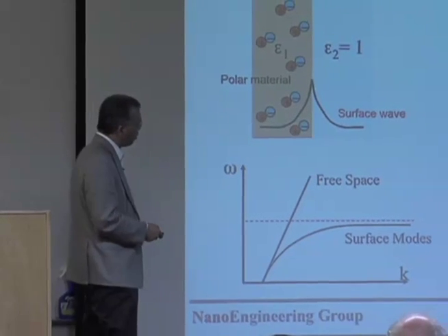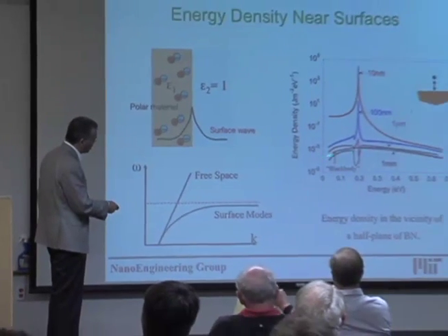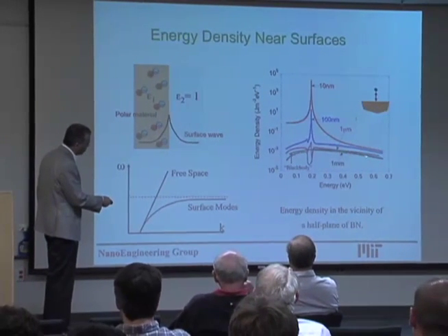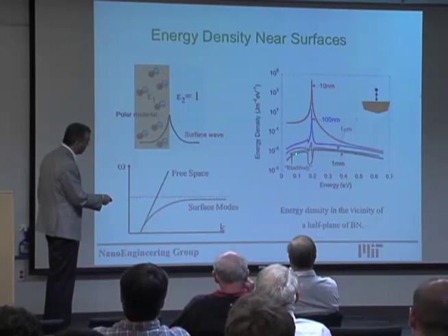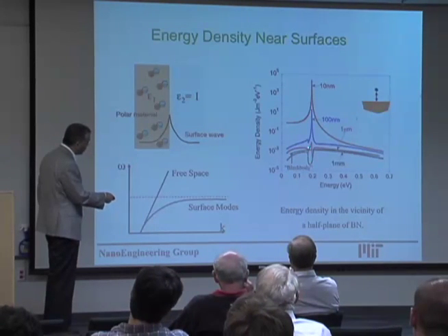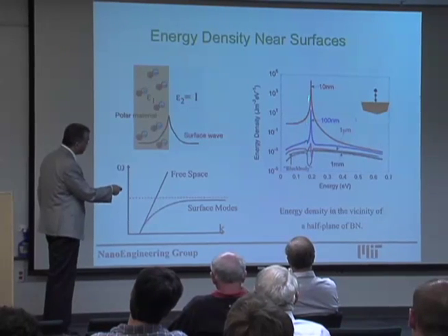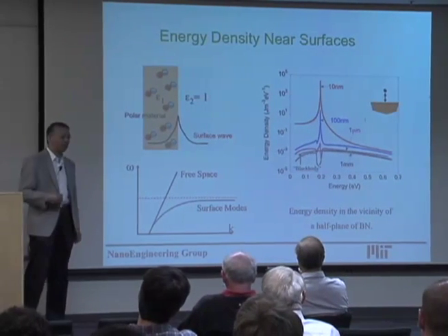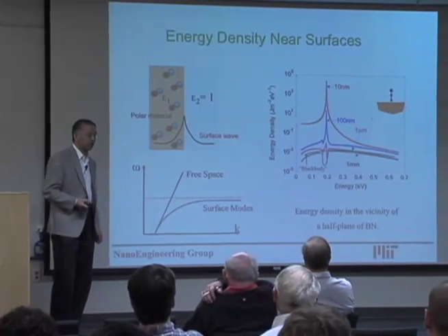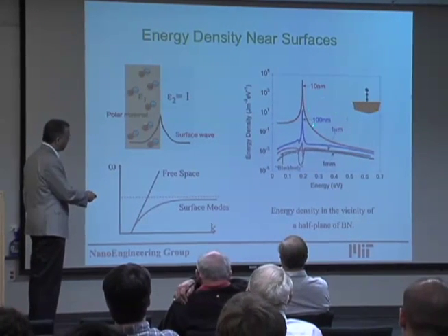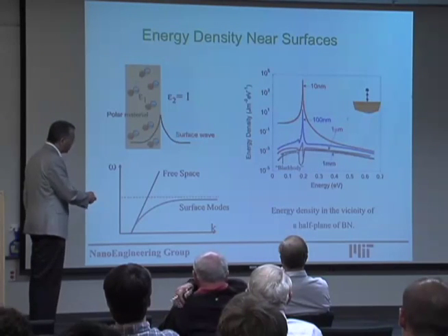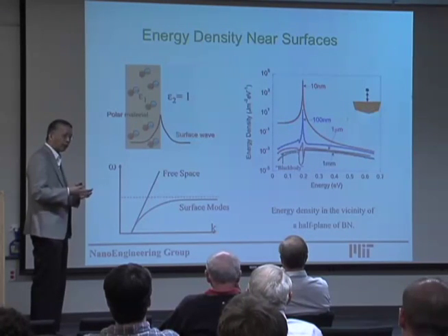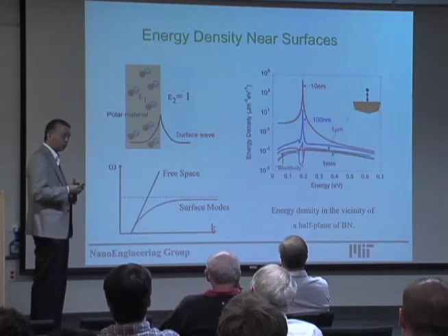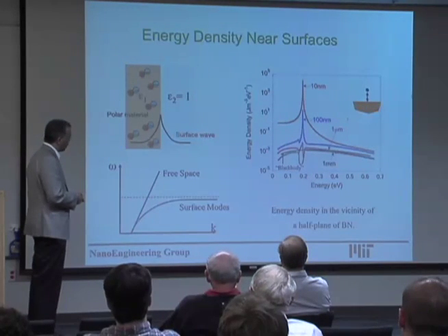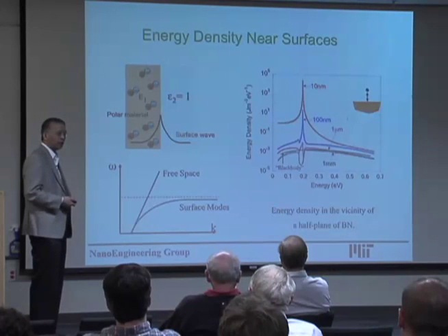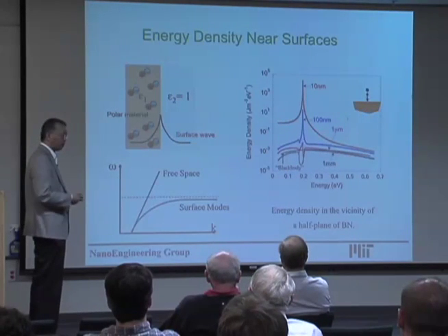So here is a calculation of the energy density of states. Here is blackbody radiation, black bodies in free space. And because of the resonance, you can see here the energy states are many orders of magnitude higher than the free space density of states. And so again, when we bring another surface close by, the tunneling will happen. And in this case, because of the high density of states, you can have a very large increase in the thermal radiation from one surface to the other.